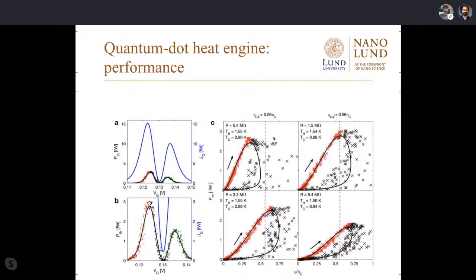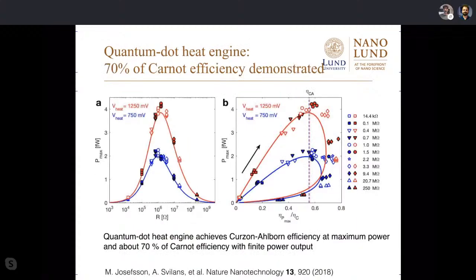But what we did instead is we did these loopy graphs for different load resistances. So it's a form of load matching that we do here, in this case by trial and error. And then we said, fine, we cannot really extract anything about the maximum efficiency regime, but the maximum power points for each load resistance, so there is different behavior for each load resistance, we can actually extract quite reliably. So extracting now for each load resistance the maximum power that we can get and the efficiency at that maximum power, we can then do summary loop graphs.